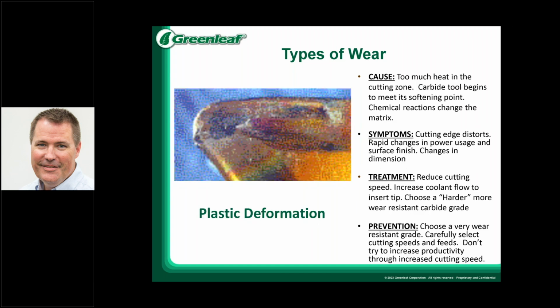Plastic deformation, this is where you end up getting too much heat into the cutting edge itself. The carbide itself is, because of the heat, softening. You'll see where the entire form, and this picture is a little grainy, it was tough to get a great picture blown up on this, but the edge itself distorts. You start to see where the chip form may widen, or you'll see an actual groove being formed because of the heat into your carbide inserts.